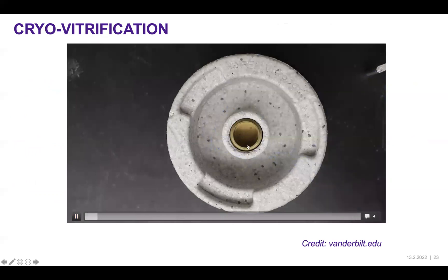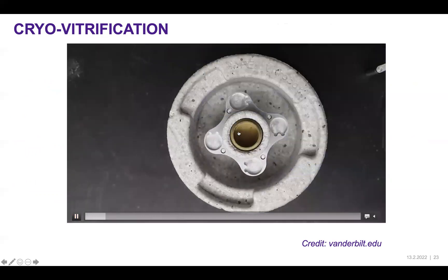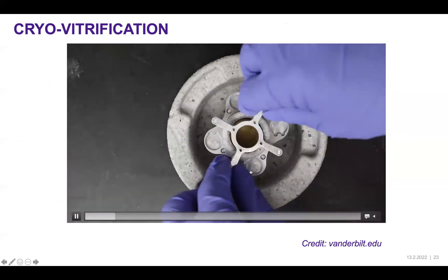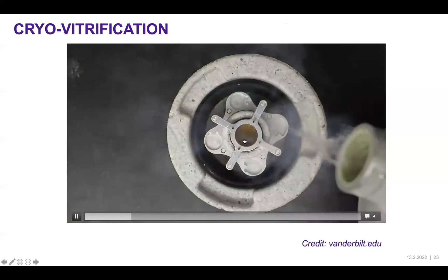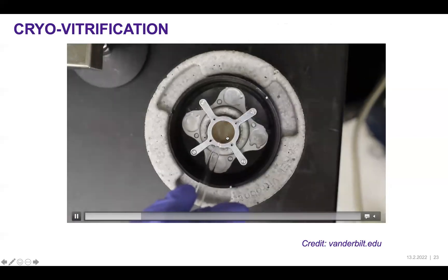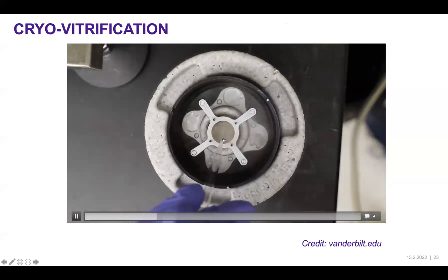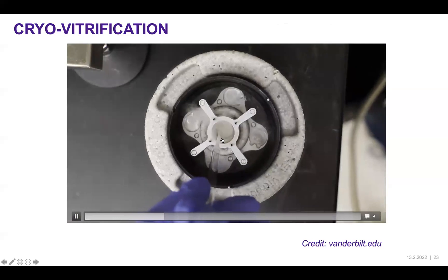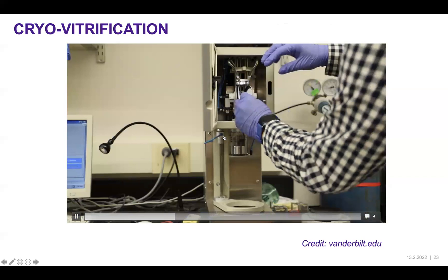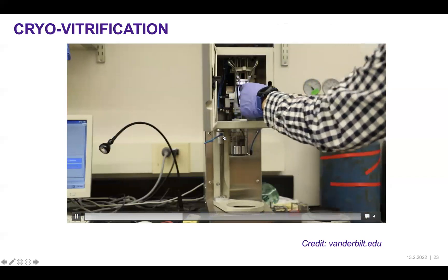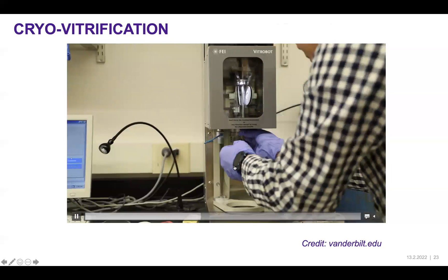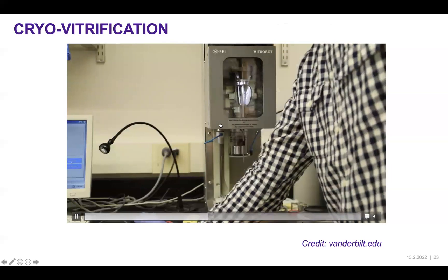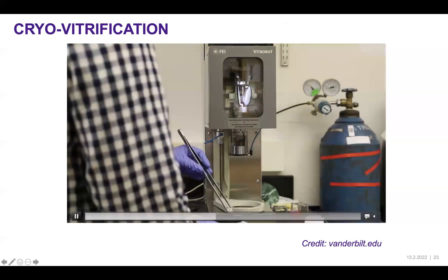Here is a video showing how the entire process is done. You cool liquid ethane or propane in a bronze cup. Outside, liquid nitrogen is added and cooled, and a spindle conducts heat to cool the bronze cup very rapidly to minus 185 or minus 190 degrees Celsius. Liquid ethane or propane or a mixture is passed in and condenses at this temperature. Before plunging, you use a dedicated vitrification robot and attach your grid using tweezers.